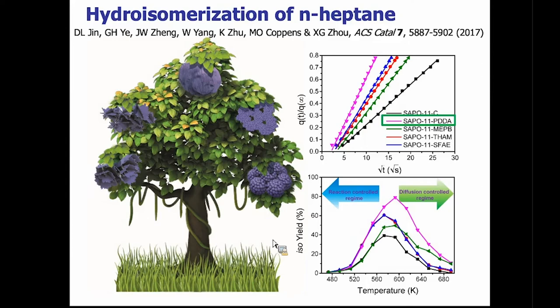That is, if your temperature is very low, the reactions are very sluggish, not much is happening. If the temperature is high, everything goes quickly, but it goes too quickly. The molecules can't follow, and you have diffusion limitations. So depending on the hierarchy of the materials, you have these different curves with a different maximum. And the cusp, the apex, is just at the point where you are between reaction controlling and diffusion controlling. Very similar to what you see in these natural systems. And so using these principles, you can see that the nature-inspired structure, where you hierarchically structure this material, can lead to one where you have a much higher efficiency to lead, in this case, to this isomer, the required molecule, and not to undesired side products.